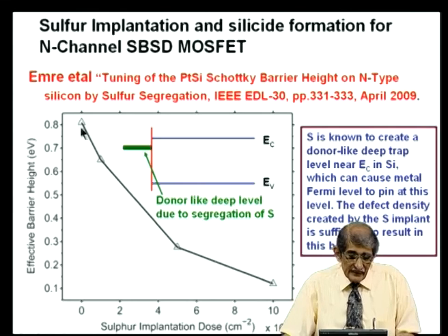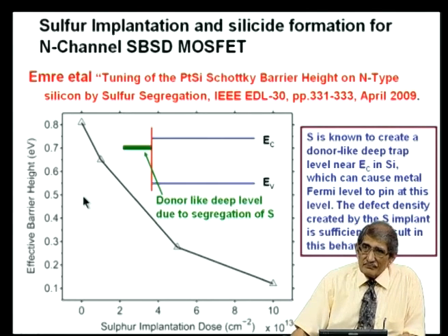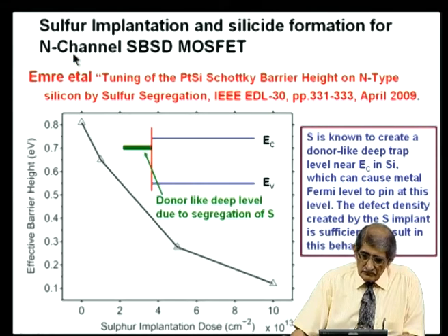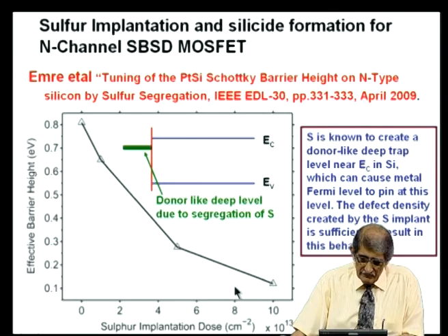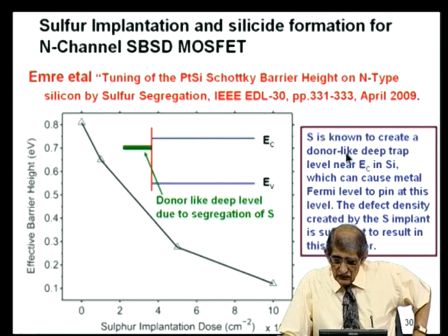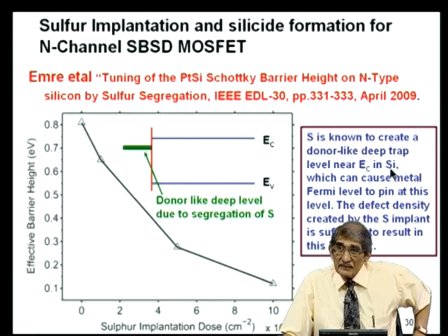Barrier height originally is 0.8 if you do not implant. If you take n-type material and make platinum silicide, it is about 0.8. But for different doses, the barrier height is reduced, even very small. They can reduce that. What they have observed is, sulfur is known to create a donor-like deep trap level near the conduction band of silicon.